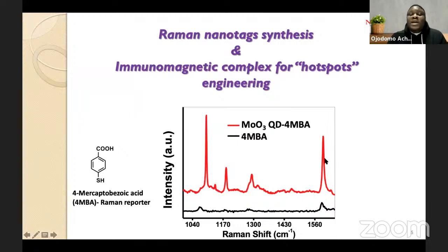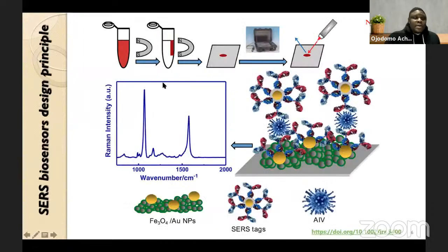So these peaks are now quite noticeable, and also this kind of preparation where you conjugate a Raman reporter molecule, such as smaller dyes, 4-mercaptobenzoic acid or rhodamine 6B, 6G, and the rest. In the presence of this plasmonic material, you can see this kind of signal enhancement. And this kind of material is what we call Raman or SERS nanotags, which are used in different applications.